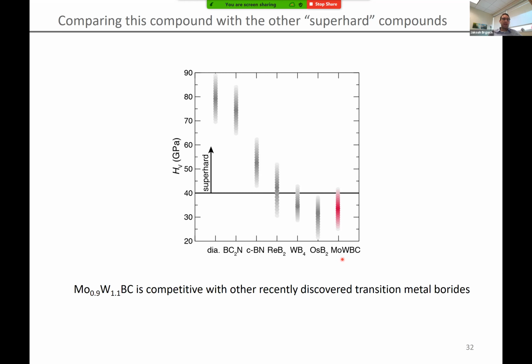But one of the things you might notice is that our goal was to identify a super hard material that falls entirely above the 40 gigapascal threshold, and we didn't quite make it there. The reason for this, as I mentioned, is that we're using an indirect proxy for hardness, which isn't really giving us an accurate idea of how to predict the material's hardness still.